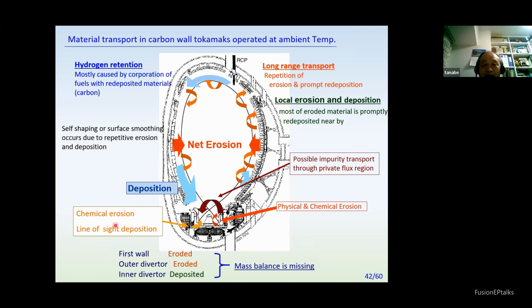So the net erosion - most of the plasma facing surface shows net erosion, and this is deposition, net deposition. But the first wall is eroded, outer divertor also eroded, and inner divertor deposited. Unfortunately, mass balance is still missing. We assume most of the eroded material comes from the first wall, but actually this is not measured. So this material transport is not completely solved.